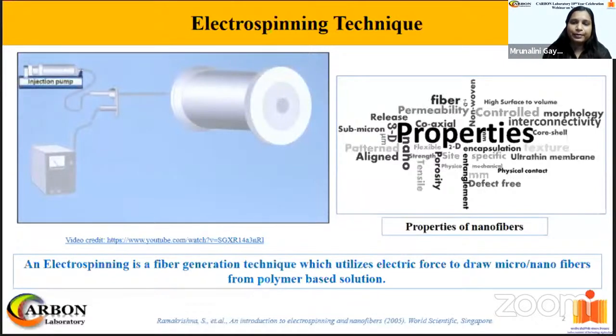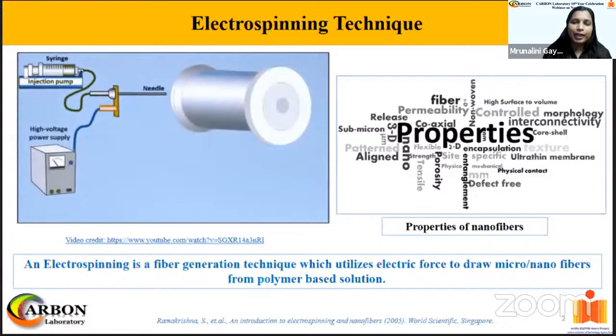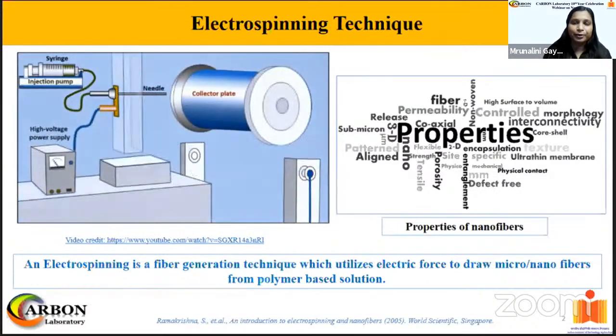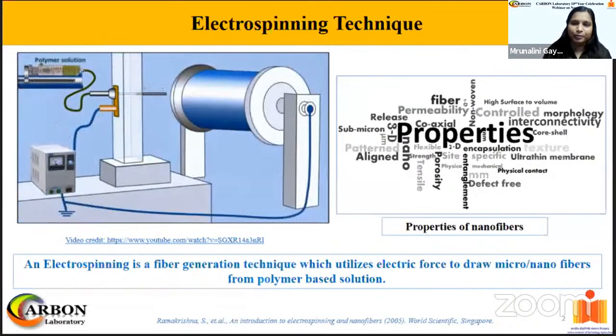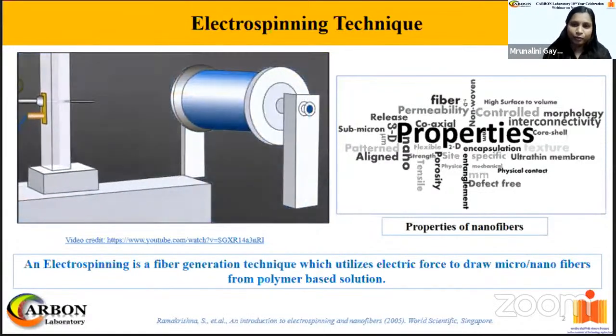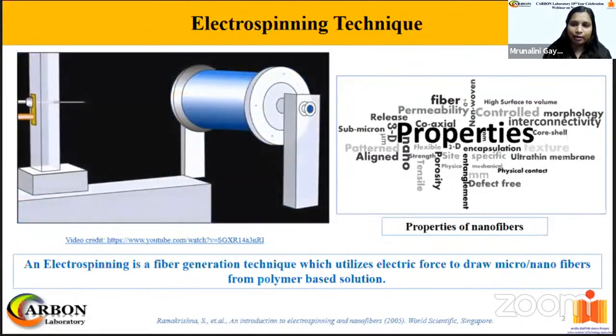We use a simple, easily programmable and scalable technique called electrospinning, which utilizes electric force to draw micro or nanofibers from a polymer-based solution. As you can see in the video, a basic setup consists of a syringe pump, a voltage supply, and a grounded collector. The polymer-based solution is loaded into the syringe and pushed at a definite flow rate. The droplet oozes out from the blunt needle, and after applying an electric field, the droplet gets charged.